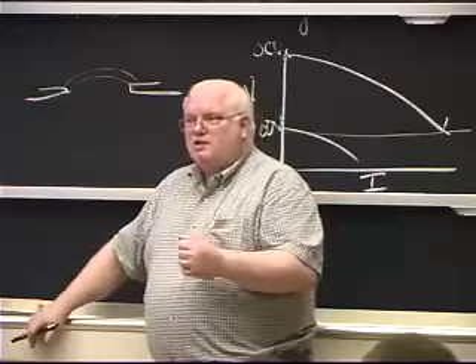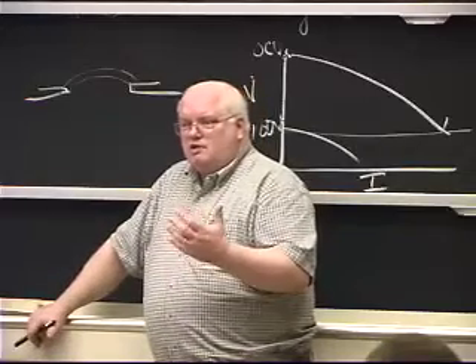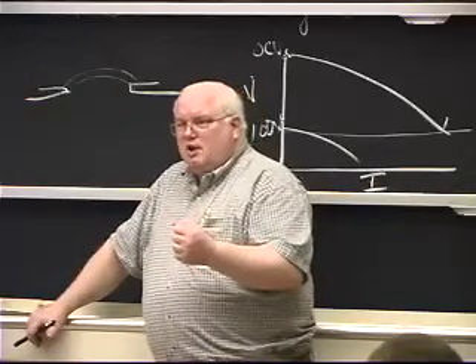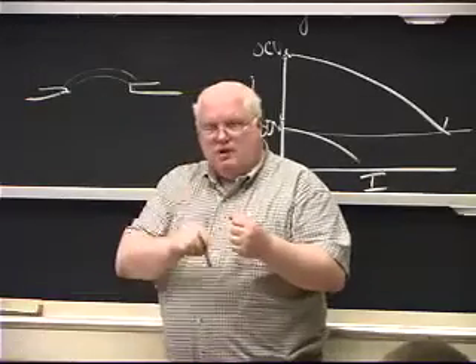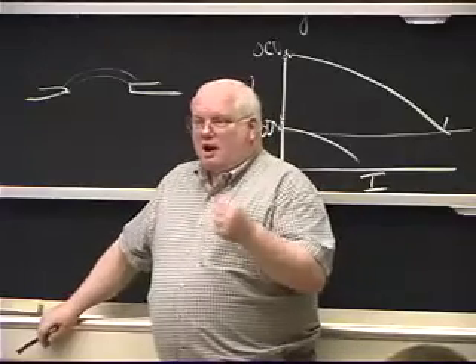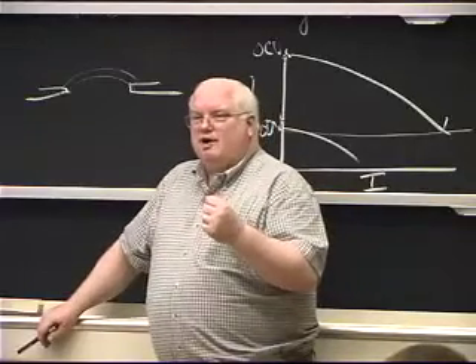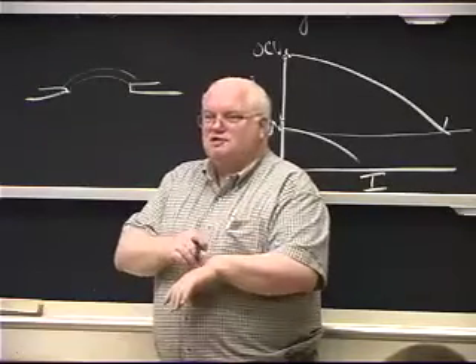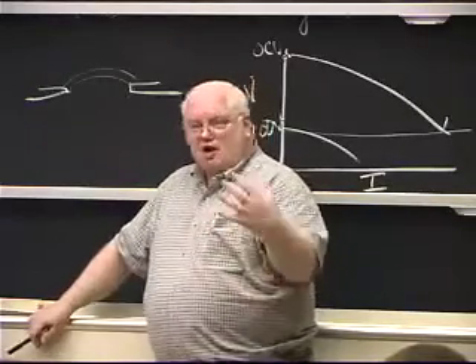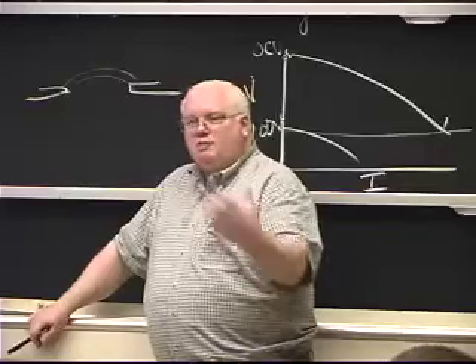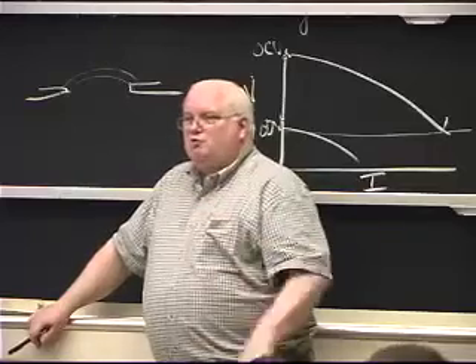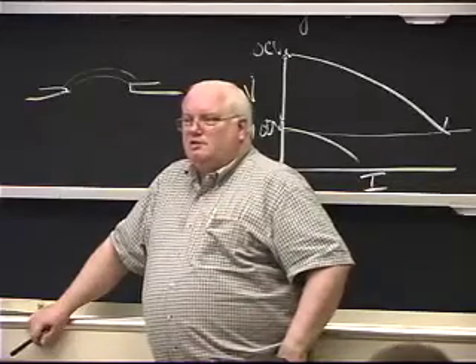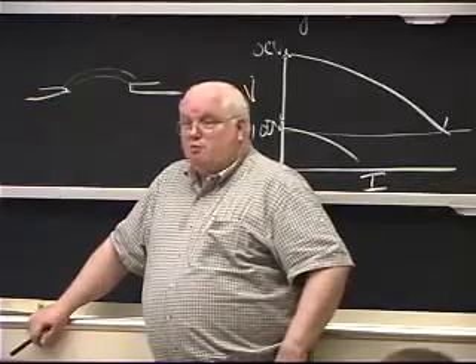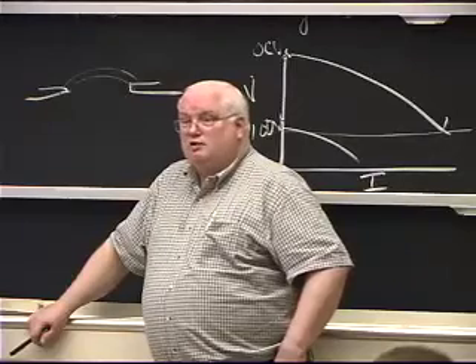I had only watched that thing for 60 seconds, 120 seconds, 1 or 2 minutes. But I was like from here to the second row here, and I had gotten a sunburn. I finally realized what it was. It was from that 2 minutes of watching that high reflectivity aluminum 600 amp arc had sunburned my skin in 2 minutes. Now if that had been my eyeball, I probably would have been blind in 2 minutes.